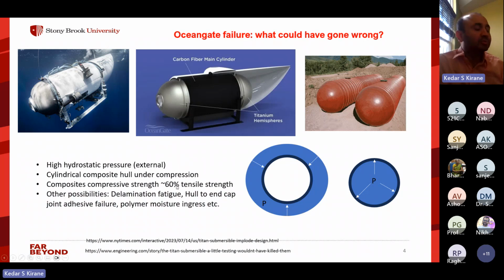Of course, personally, I'm not sure. It is all speculation at this point, and there could be many other possibilities. Delamination could be happening between the layers and growing by fatigue. These two dissimilar materials were joined by a glue, and under moisture the glue could have potentially degraded. The polymer could have been degraded due to potential moisture ingress and so on. So there are many reasons, and actual forensic analysis would help.